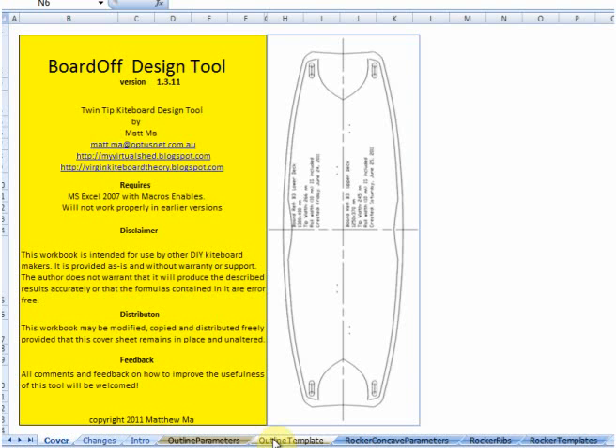It turned out to be a really interesting exercise and I found it to be a particularly useful design tool, not because the numbers that come out of it can be particularly relied on. The theoretical values that I've plugged into that model can vary quite dramatically from the actual values. For example, the elastic modulus of your core material can vary wildly, as can the properties of your fiberglass and your resin, and it can vary according to how you go about doing it. Resin, for example, is impacted a lot by relative humidity, dry conditions, whether it's post-cured, elevated temperatures, all these kind of things. But it's actually very insightful in helping you get an understanding of trading off between pairs of parameters.